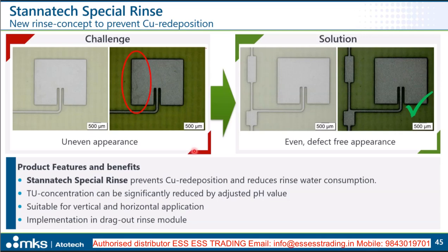It works by using thiourea, which is already known from thiourea rinsing, but with the additive, it's possible to significantly reduce the thiourea consumption in the rinsing and also to reduce the rinse water consumption. This can be applied in vertical and horizontal, and it's implemented directly in the drag-out rinse module. It's a drop-in for existing lines, and it also helps to prevent discoloration defects on the immersion tin pad after the rinsing and drying.